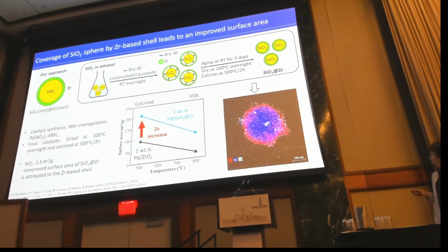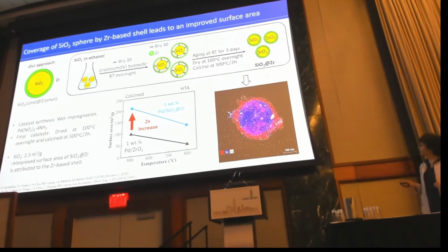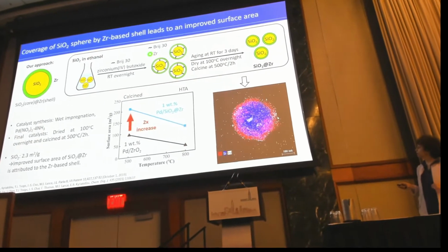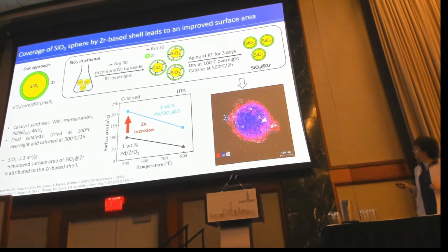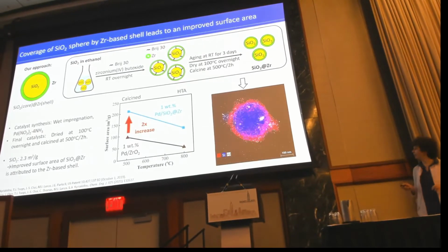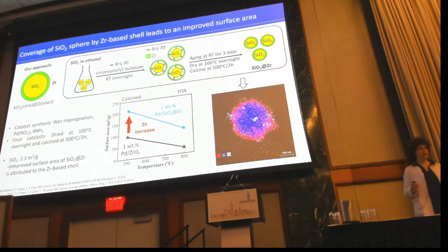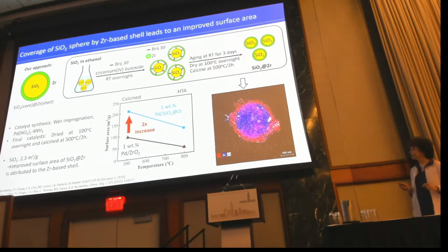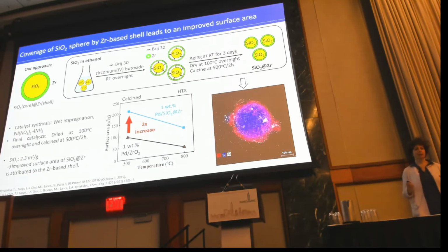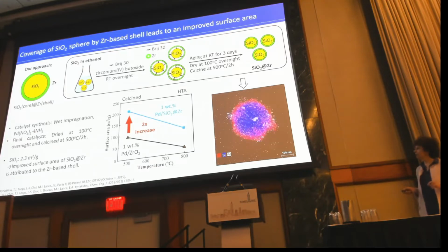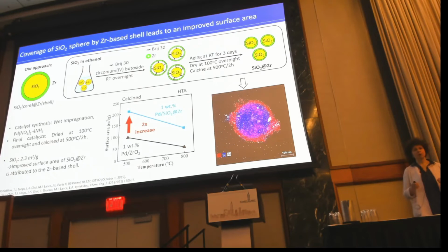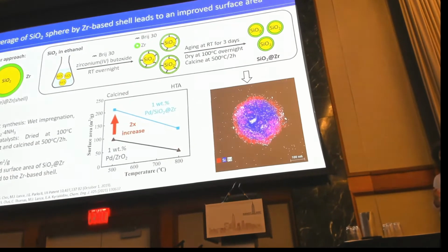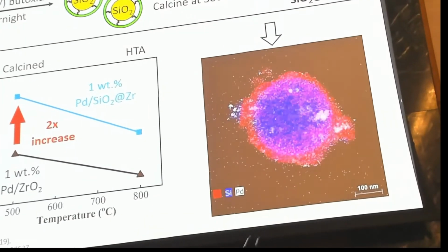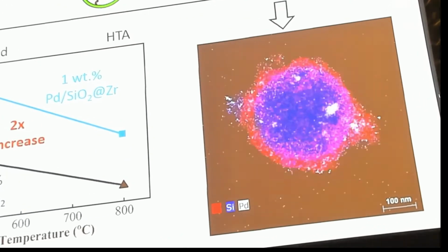And also, if you look here, the surface area after aging at 800 degrees C is almost 110 square meters per gram for the palladium on the core-shell support. This was very exciting. So we want to investigate this material even further. Another important piece of information here is that the silica core itself is almost non-porous and has a very low surface area of around 2.3 square meters per gram. So basically the enhanced surface area that we observe on this material is attributed to the zirconium shell and not the silica core.